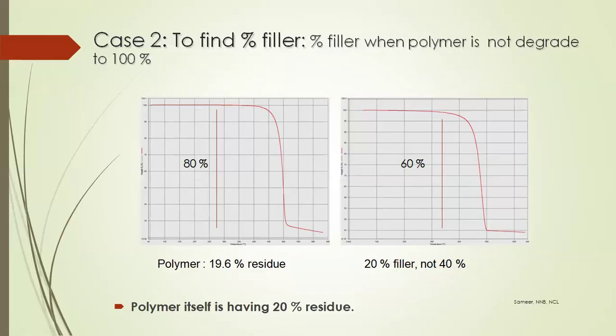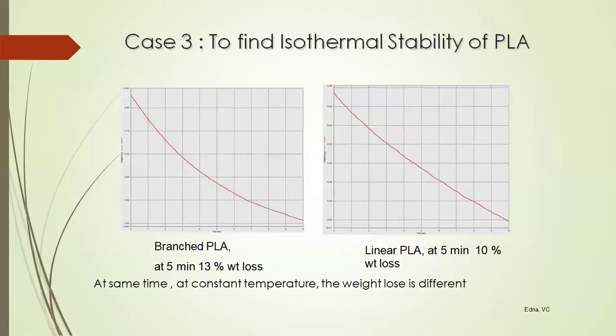Now, what if your polymer is not degrading 100%? The polymer itself is giving residue. So this is the rare case where your polymer itself is giving me 20% residue. And when you do a TGA of your polymer with the filler, it is giving me 40% residue. But now remember here, out of this 40%, 20% residue is of my polymer. So actual filler content is only 20%, not 40%. Right? So remember these small tips, which will be helpful in manufacturing and in research